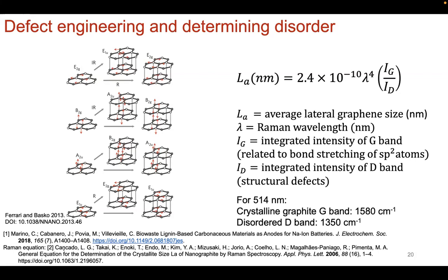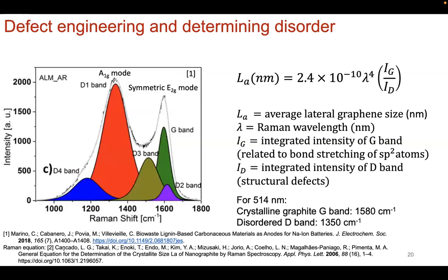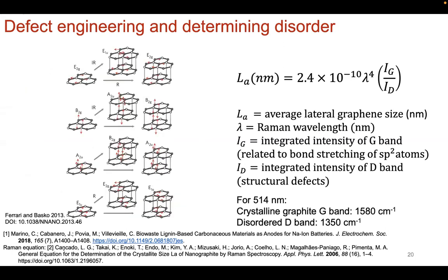You just take the general integrated area using, let's say, a fitted Lorentzian curve, but you can break it down even more. Instead of just the D band here and just the G band here, you can really break down these modes into this D1, D2, D3, and all of them are tabulated like so.